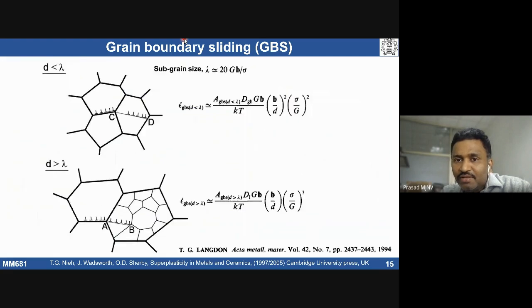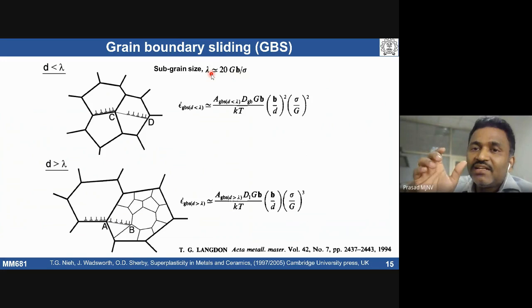So accordingly, we know that a subgrain structure is going to form when you deform material at high temperatures. The subgrain size is related to 20 Gb/sigma, typical for metallic materials. G is the shear modulus, b is the Burgers vector, and sigma is the stress. So for a particular material, if I deform it at a given temperature, I know what subgrain size it is going to form.